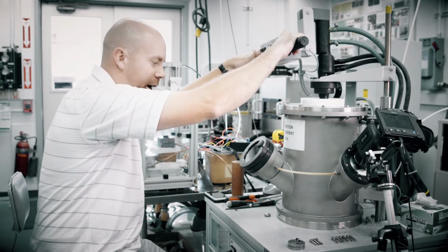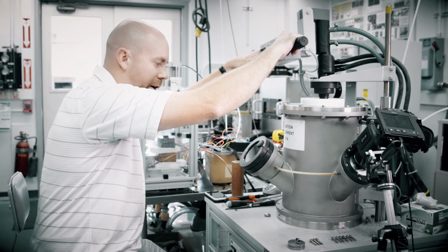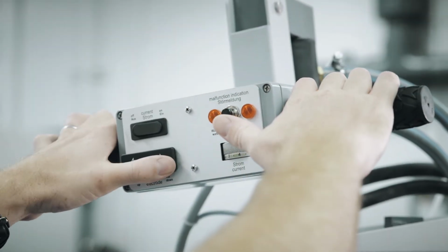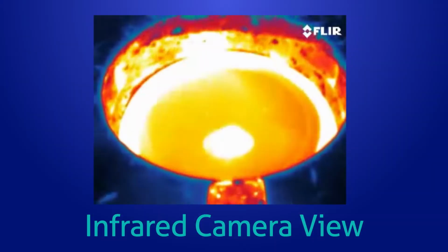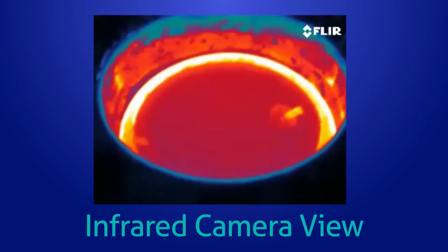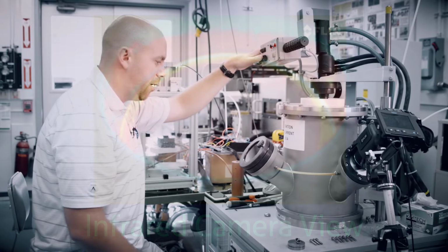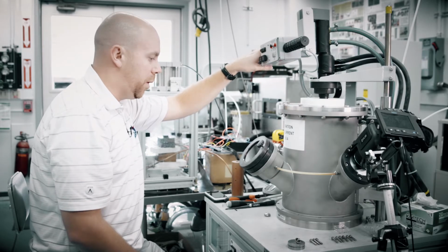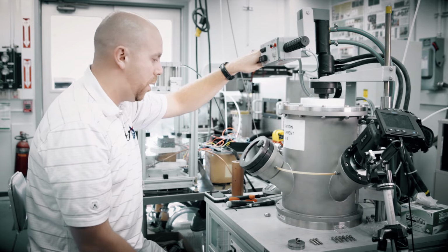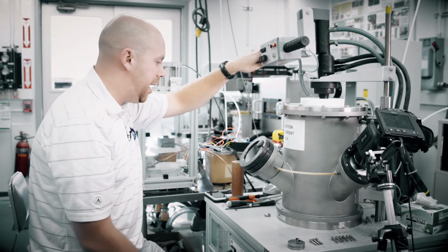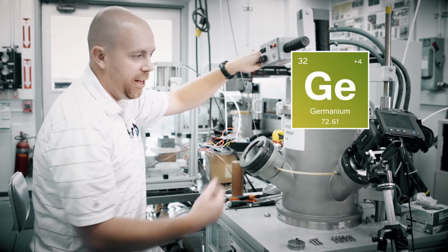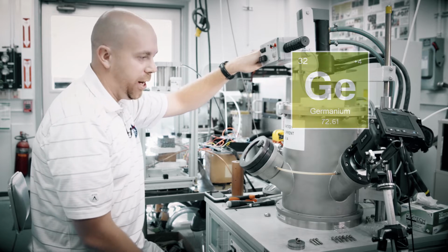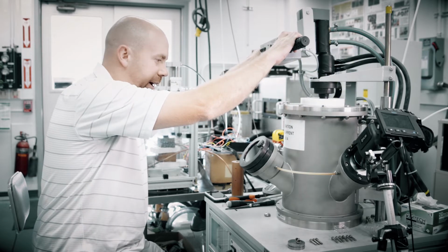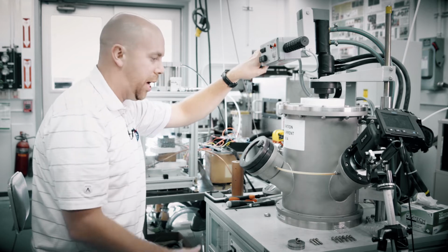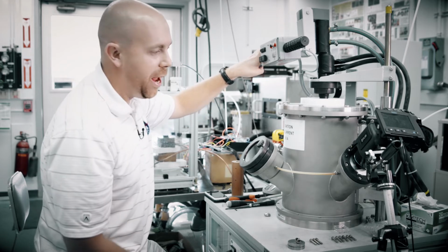So right now I'm putting 168 amps at 12 volts through a sample, and you can see in the infrared camera that I'm melting a piece of pure titanium with the arc melter. This is a FLIR infrared thermal camera, and we are looking into the chamber through a vacuum-tight germanium window. At the wavelengths of my camera, germanium is transparent. So we are able to film through the chamber through an optically opaque window.